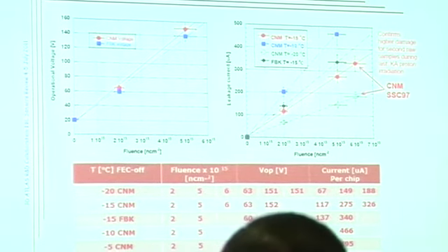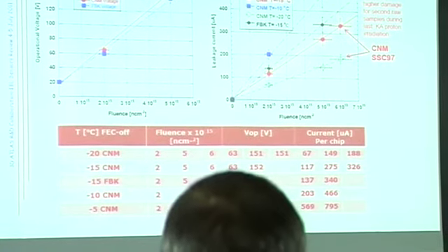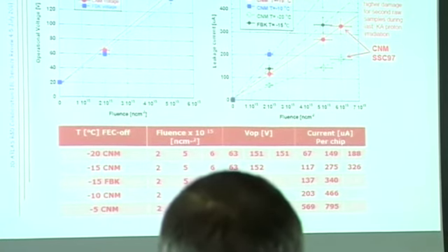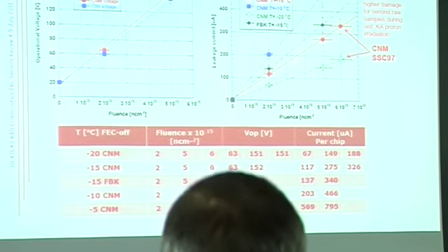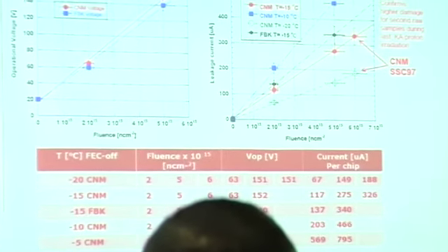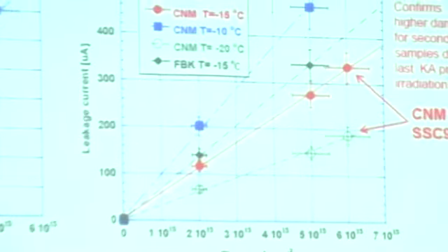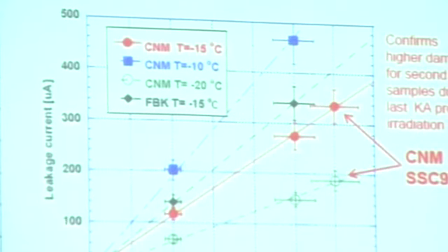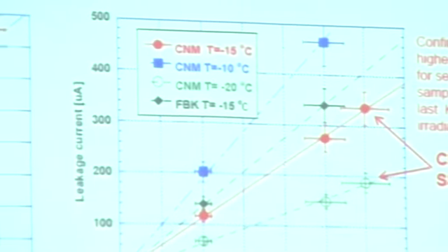So, of course, we had some time during the test beam and also in the lab to measure leakage currents and operational voltages. Here I have a compilation of the values that we obtain after irradiation, because of course this is quite important for the system aspects. You have that, for both CNM and FBK, the operational voltages don't lie on a straight line. Of course, it depends on the temperature, even if all operational voltages were maintained at all temperatures at which we took the measurements. And here you see leakage currents versus fluence at 4 temperatures, and those were the temperatures measured in the climate chamber. So we are not really making any correction of the temperature you see there. It is really the temperature measured in the climate chamber.